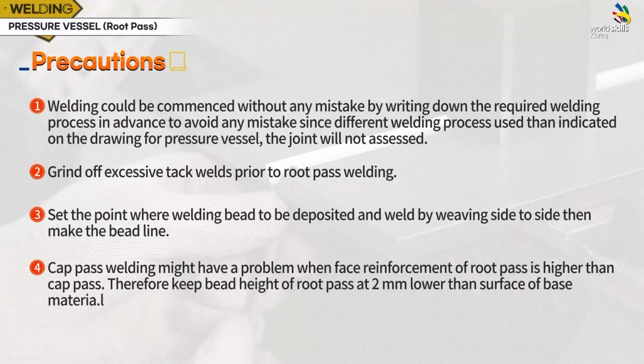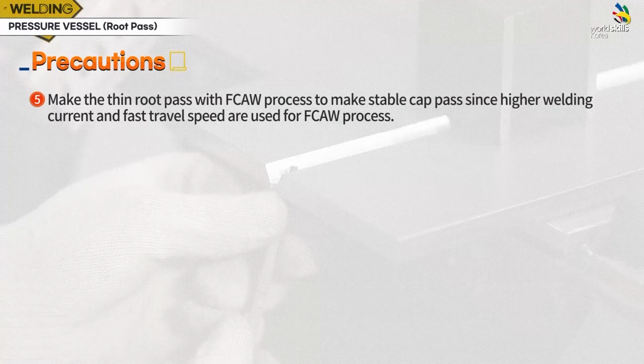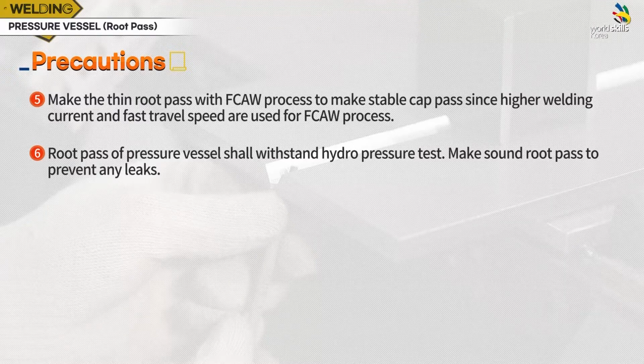Cap pass welding might have a problem when face reinforcement of root pass is higher than cap pass. Therefore, keep bead height of root pass at 2 mm lower than surface of base material. Make the thin root pass with FCAW process to make stable cap pass, since higher welding current and fast travel speed are used for FCAW process. Root pass of pressure vessel shall withstand hydro pressure test. Make sound root pass to prevent any leaks.